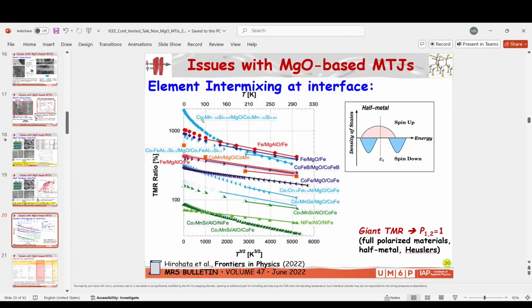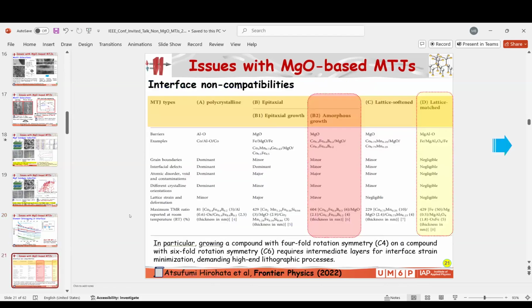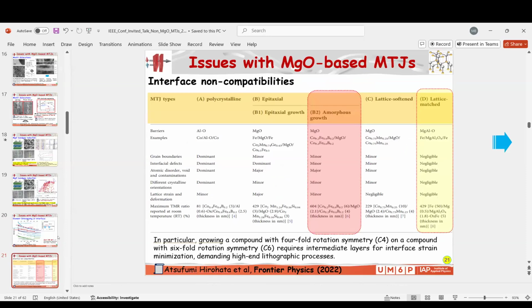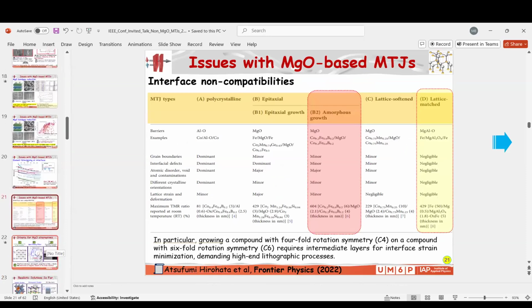But for example, for the half metallics, normally we expect the performance to be high at room temperature, but this is not the case. This was explained by the elemental diffusion, also the mixture of elements constituting the Heuslers at the interface, plus the oxidation. So this is somehow the shortcoming of MgO. But still, MgO, I repeat, we are not at the phase to replace MgO yet, but it could be done in the future. This is the comparison with amorphous and lattice match.